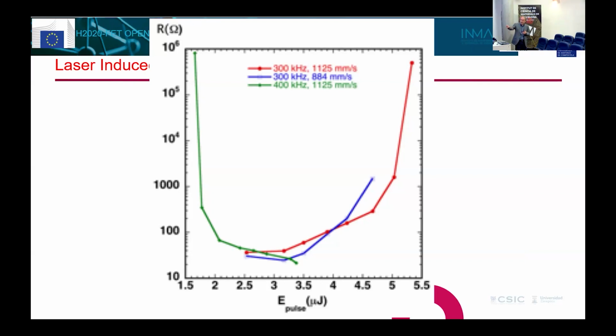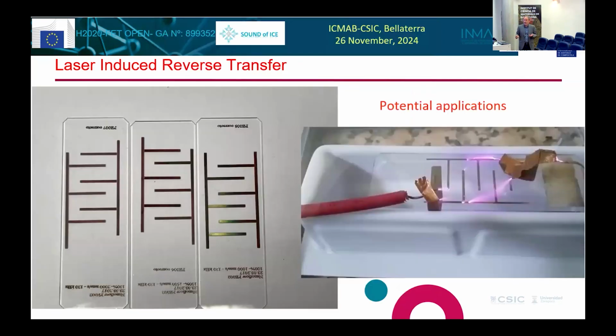Here we change the frequency of the laser and we change the speed. In these lasers, when you change the frequency, you change sometimes the pulse width, or you change other factors, and you change the energy per pulse, which is very important. So most lasers, you change the energy per pulse when you change the frequency, and that's how you change these values. But they are very nicely controlled. And so if you make interdigitated circuits like this, you can generate a surface